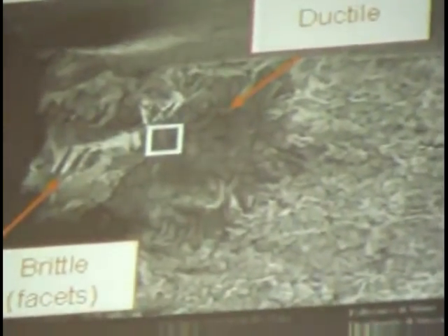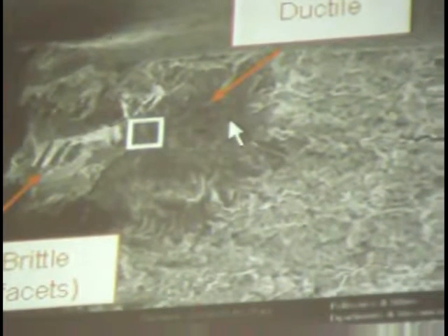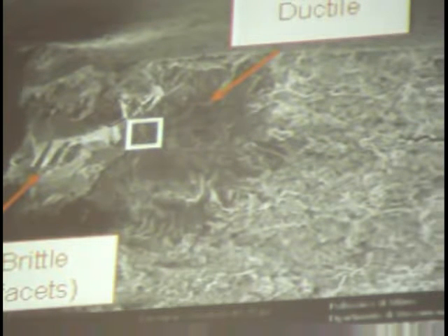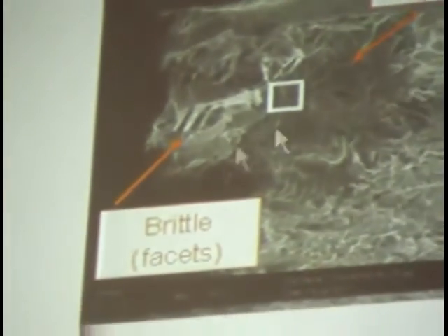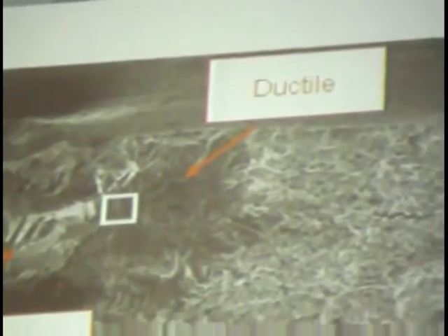Here I'd like to show you just two examples. We analyzed at the SEM all the fracture surfaces for all the positions in the prismatic sonotrode, and we could observe that typically the defects at the initiation site were only of two different kinds. The first kind is this one. It's quite complicated. Here the initiation site was in this position, and on the left side we have a brittle fracture, the typical facets seen in very high cycle fatigue with a brittle fracture. And on the other side, instead, we had some ductile propagation, and then the final failure.